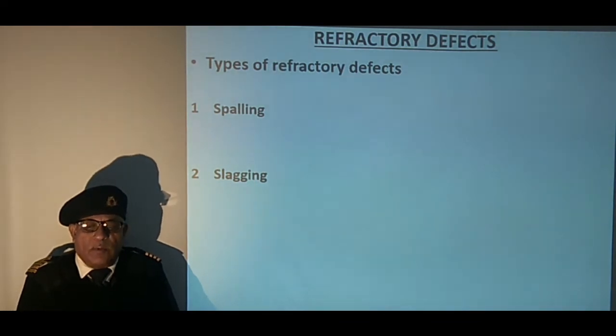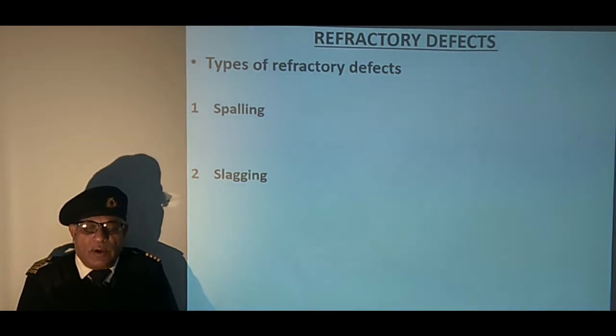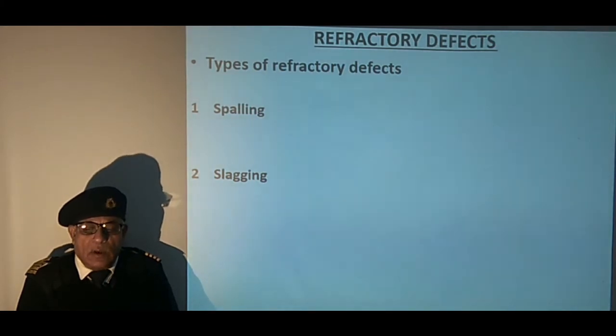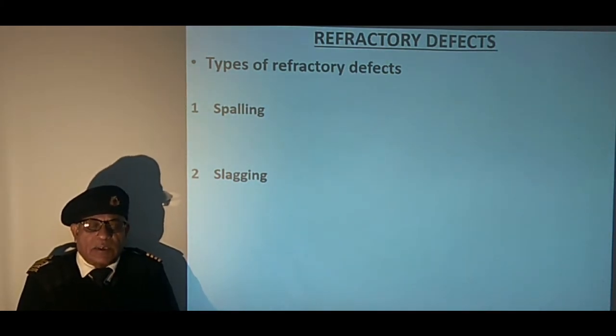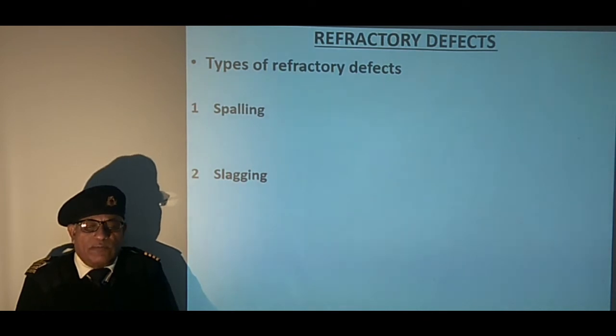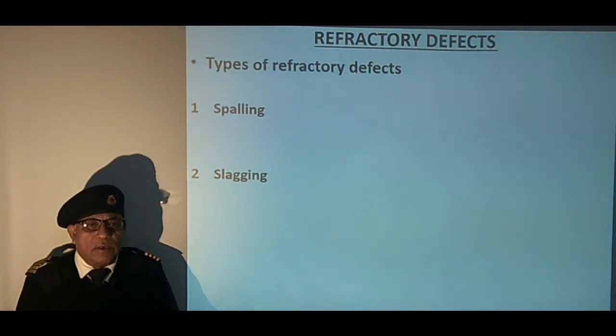Slagging is the softening of the brickwork to a liquid state due to the presence of vanadium or sodium in the fuel from sea water, which acts as flux and lowers the melting point of the brick to form a liquid pool in the furnace. Eyebrows may form above the coil and the attachment may become exposed. Material falling to the floor may critically reduce the burner clearance and reduce efficiency. Flame impingement may lead to carbon penetration in the refractory.